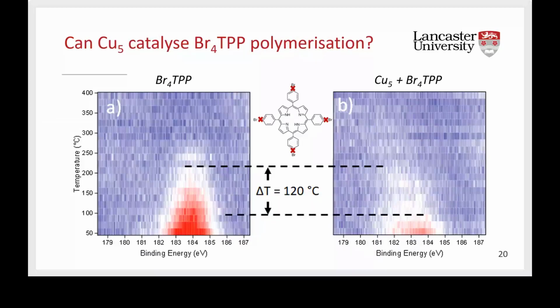And the question is, can the Cu5 catalyze the bromophenyl porphyrin polymerization? As catalyzing a reaction involves chemistry, we have a suitable tool to study it, which is the XPS. So in figure A, you can see some XPS measurements, where on the x-axis, we have the binding energies of the electrons on the 3p orbitals of bromine atoms. And on the y-axis, we have the temperature of the substrate. So we are heating up the substrate to induce the polymerization.